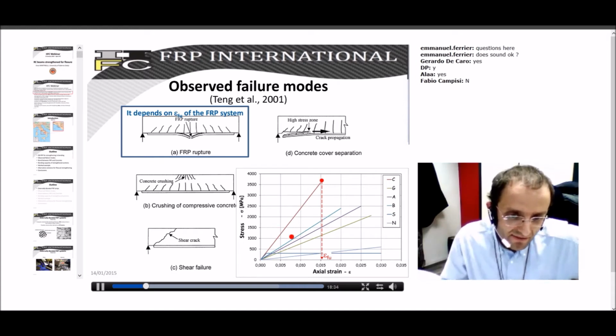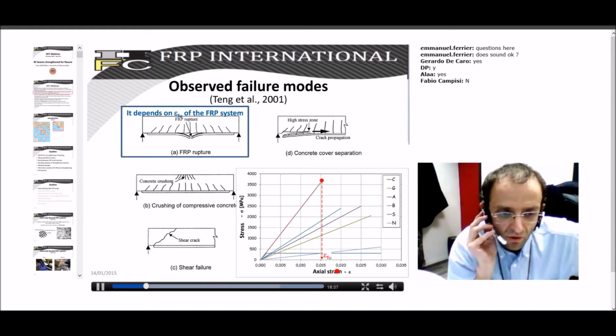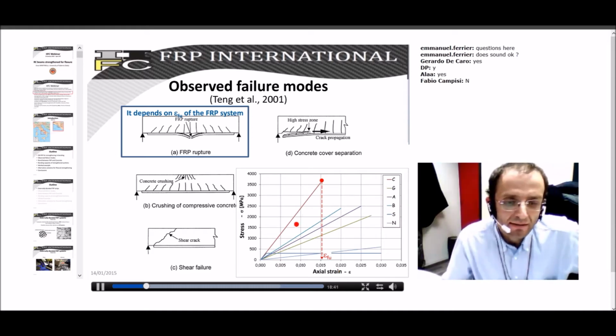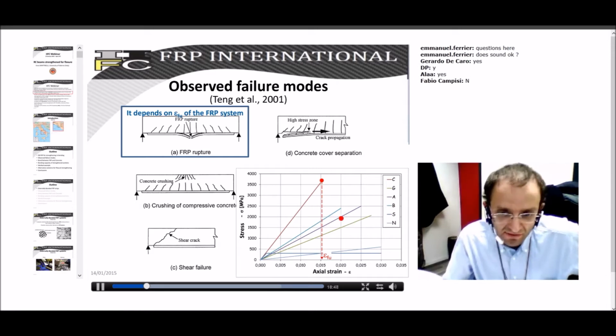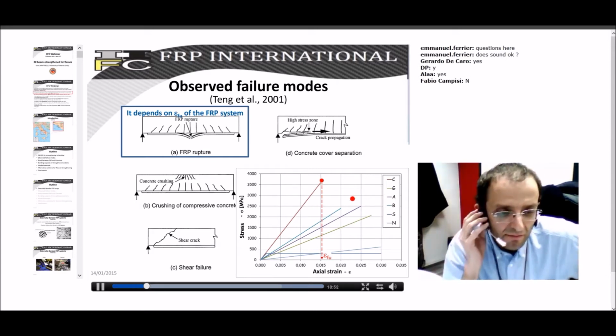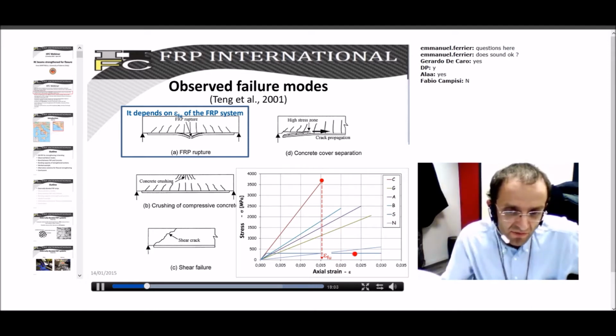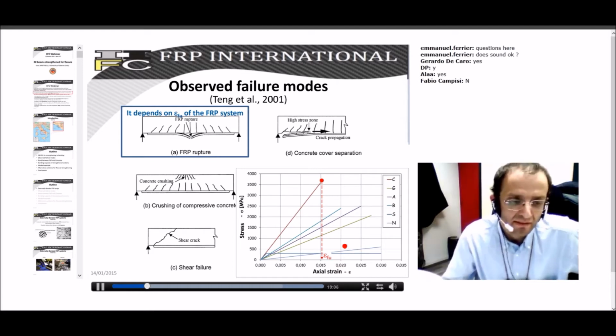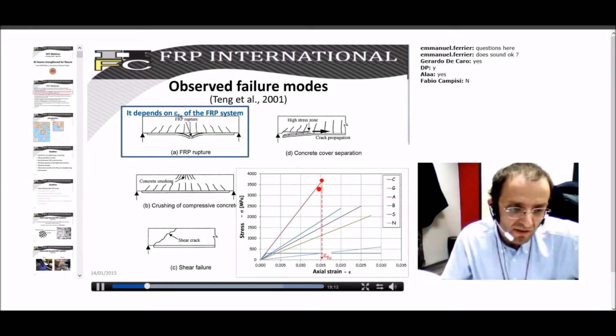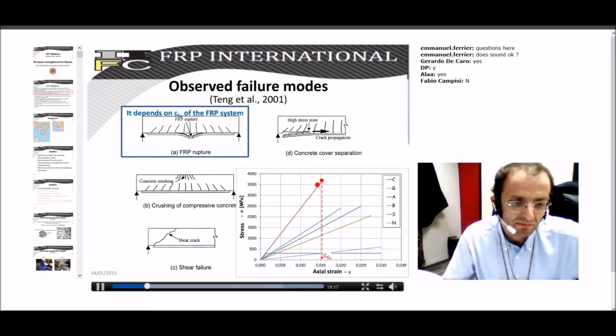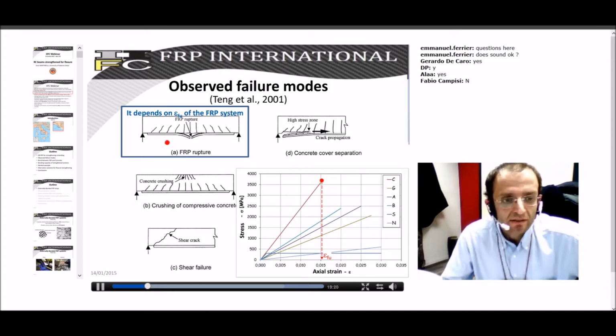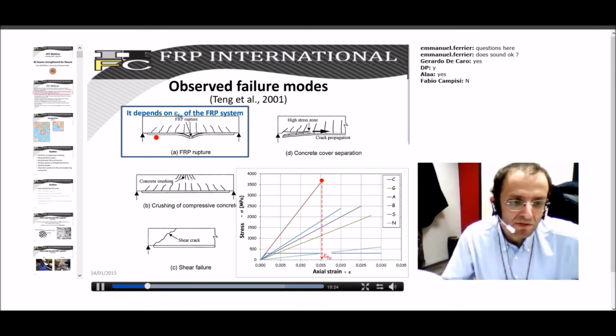And you see here on the right a stress-strain diagram, which on the one hand highlights the fact that these materials, especially carbon, but also glass and also aramid, these are the three curves, fiber reinforced, are usually characterized by a quasi-elastic and elastic brittle behavior with respect to the elastic plastic behavior which is characteristic of steel. So on one hand you have a material which can be even significantly stronger than steel, but can also be rather more brittle. And so this is the first failure mode which is peculiar for these FRP strengthened systems.